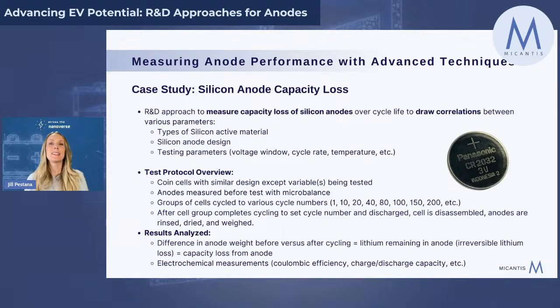So silicon is a really interesting anode material because it has extremely high energy density compared to graphite. It's an order of magnitude more. So instead of around 300 milliamp hours per gram, you're getting nearly 3,000 or more milliamp hours per gram. Those are just rough estimates. So super high energy density, but because of this, the types of analysis you can do on it offer new opportunities.